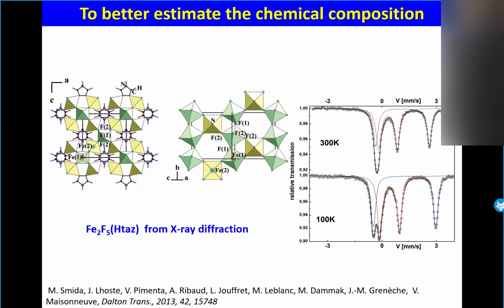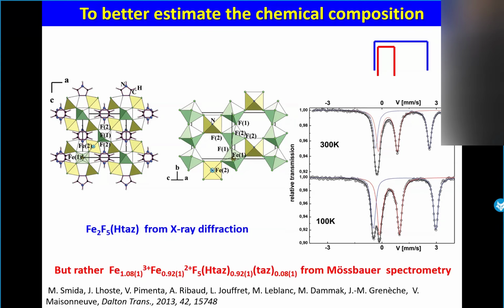It's much more difficult. So when we looked at the spectrum at room temperature, first you have 3 lines. How to describe these 3 lines? Of course, you have 3 main lines, which can be divided in 4 lines with the same intensity, because it is a powder. So now, how to associate the different lines? Because you have different solutions. And if you look at the chi-squared, you cannot distinguish. So you have such a solution, there is no physical meaning. You have another solution, and the last solution corresponds to this one.